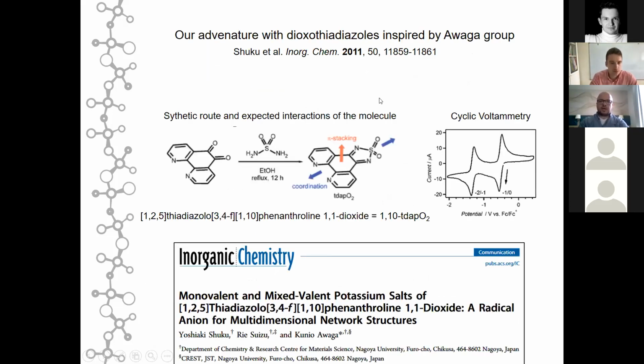So as I said, our adventure with dioxothiadiazoles was inspired by the work of Kunio Awaga, reported in 2011, where he combined a phenanthroline alpha diketone, a phenanthroline backbone, with sulfamide and obtained this kind of compound, which has coordination abilities on one side, and the dioxothiadiazole, which is redox active, on the other. It is a completely rigid molecule without any dangling chains, so easy to incorporate in systems in a rational way.